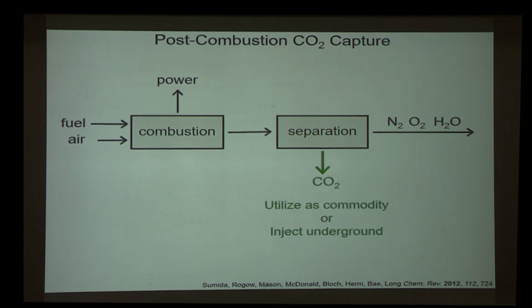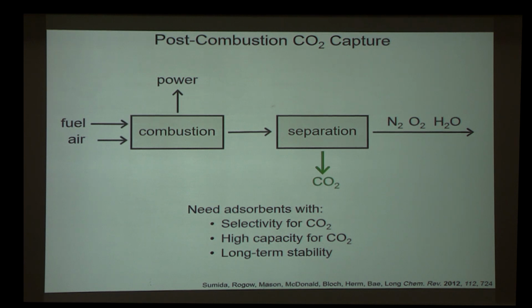Now that we've isolated CO2 from the gas stream, what do we do with it? That's a very important question. And there are two choices. One, we could utilize it as a commodity, for example, as a building block in chemical synthesis. The other is that we inject it underground at high pressures for more permanent sequestration. My talk will not focus on this issue, but instead I will focus on the separation step. How do we actually pull CO2 out from that gas stream? And what we need is an adsorbent that has high selectivity for CO2 over these other gases. We would like something with high capacity so that we could use only a small amount of adsorbent and still capture large amounts of CO2. And finally, we need long-term stability, because any adsorbent in this type of process would need to be used many, many times over a long time period.